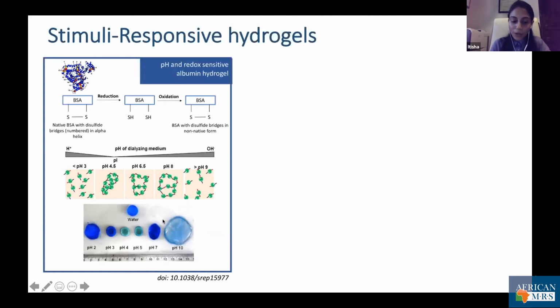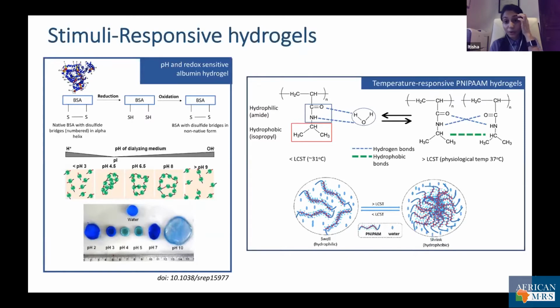Now, another commonly used thermoresponsive hydrogel is based on PNIPAM. The thermoresponsiveness of PNIPAM is attributed to its hydrophilic amide group and hydrophobic isopropyl group, which above its lower critical solution temperature form intermolecular hydrogen bonds or hydrophobic interactions so that they gel at physiological temperature. So these are interesting systems that can be used in TE to, for example, form in situ hydrogel so that when injected, it can instantly form the hydrogel under physiological condition.